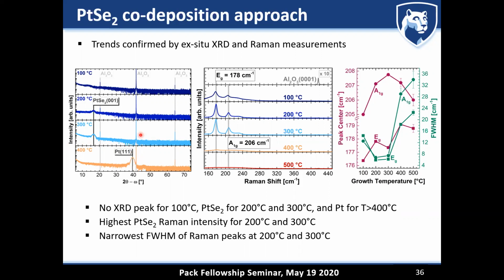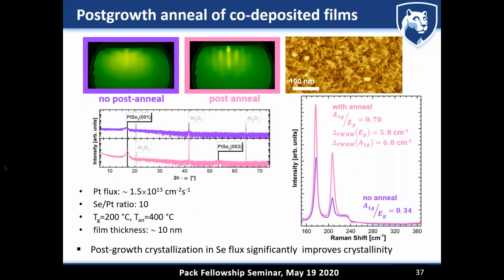This also correlates properly with the Raman analysis that we've done. It basically means that you have to limit your growth temperature to about 200 to 300 degrees C. We decided to go with 300 degrees C, but you have another trick up your sleeve. As you've grown the right phase, you can do a post-growth selenization anneal, where you stop growing but anneal the platinum diselenide to a higher temperature. When we do this, we see quite an improvement in the RHEED pattern, and also in the crystallinity, measured both by X-ray diffraction and in Raman spectroscopy. You can see that the specific Raman modes are much more pronounced.